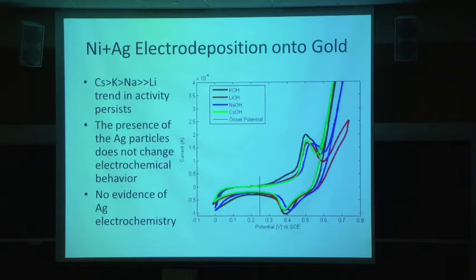Okay, if we add a little bit of silver, it doesn't have any effect on the electrochemistry, so we co-deposit silver in there so that we get the SERS effect. And these are what the cyclic voltammograms look like. Here again, you can see the red peak is the weakest. That's the lithium hydroxide. And the greenish peak is cesium. It's the most active. And then these peaks right here are associated with nickel 2+, 3+ oxidation waves. And then the space in here is related to capacitive charging. So this was missing in the previous plot that looked like a smooth rise because the previous plot was steady state, and this is cyclic voltammetry. Okay, so what we want to do now, this is just another way of seeing that lithium hydroxide is least active, cesium is most active, and we're interested in knowing what is the surface structure at each of these different places.